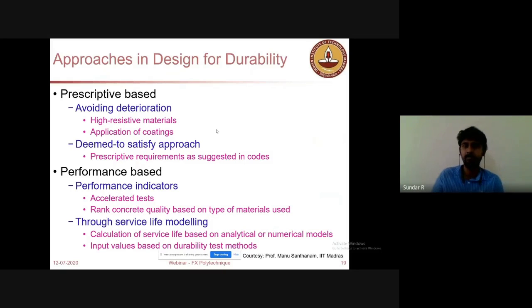And the performance based approach is where you give some performance indicators to the contractor who is going to execute the job, and you ask the contractor to demonstrate this performance in the concrete that has been cast at the site. So you have to cast the concrete at the site and take some concrete cores, or even take dummy specimens, and then see whether the performance specifications are being met. So that is the performance based design. For that, we have performance indicators through accelerated tests for chloride, carbonation, everything, and even for sulfate attack. And we will be ranking the quality based upon the type of material used. So that is the first step.